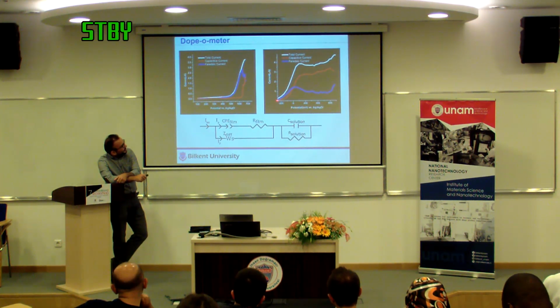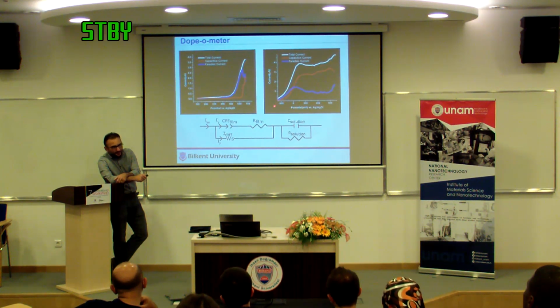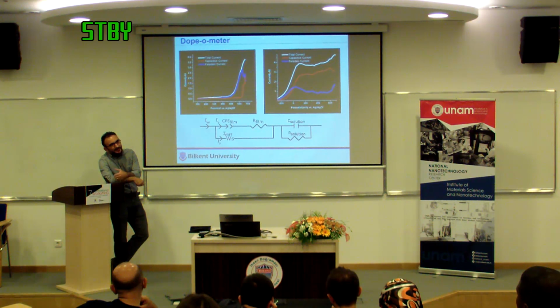So what happens is when it's in the reduced form, the capacitance is low. As it's getting oxidized, the capacitance starts going high. And then, once the oxidation starts dying down, the capacitance is roughly constant. It's rising a little more because of the coherence length distribution of these things. And these are two different polymers. This is PEDOT, this is polythiophene, and they both show similar behavior.